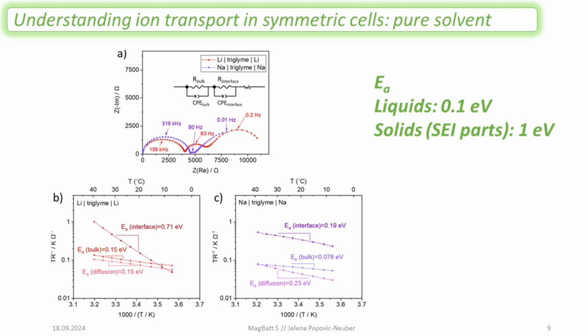If we can measure the activation energy of these three different processes that are in series, and we know what the activation energies of typical materials are, because we have studied this for the last 30 years. We know that for liquids, our typical activation energy is around 0.1 electron volts. And in the case of SEI parts, these are solid state, and we know from their defect chemistry that their activation energy is around 1 electron volt. Then we can see where our interfacial activation energies lie. In the case of this symmetric lithium-lithium triglyme cell, we see an activation energy that is around 0.7 electron volts. So it's somewhere in between the 0.1 and 1.